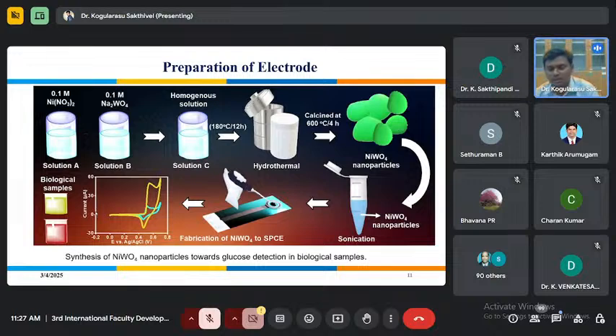So let's come to the scientific part of this work. This is how the electrode is prepared. So in this work, for developing the next generation glucose biosensors, we have used nickel tungstate. So here is the synthesis method. We use the hydrothermal method with a low temperature synthesis of 180 degrees Celsius for 12 hours. As initial substances, we have taken nickel nitrate and sodium tungstate to prepare nickel tungstate nanoparticles.